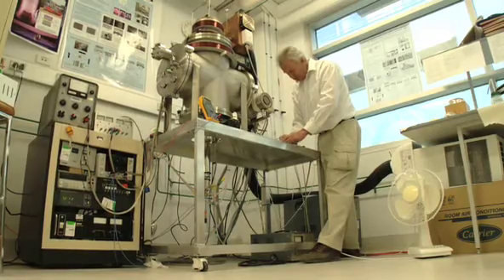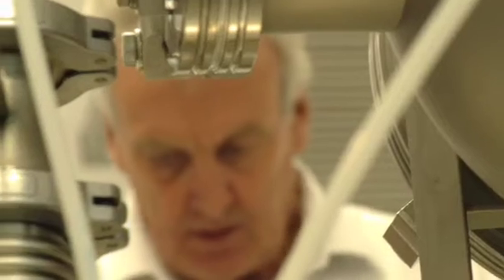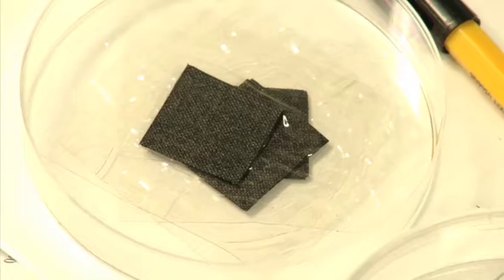At the moment, they take a carbon cloth electrode which looks like denim but is made out of carbon fibres. They put it into a plasma machine, pump it down to very low pressure, and grow little whiskers of carbon that are hundreds of times smaller than a human hair. They then deposit platinum onto those whiskers, which lets a lot of hydrogen through and makes the fuel cell very efficient — reducing the amount of platinum needed and simplifying the manufacturing method.